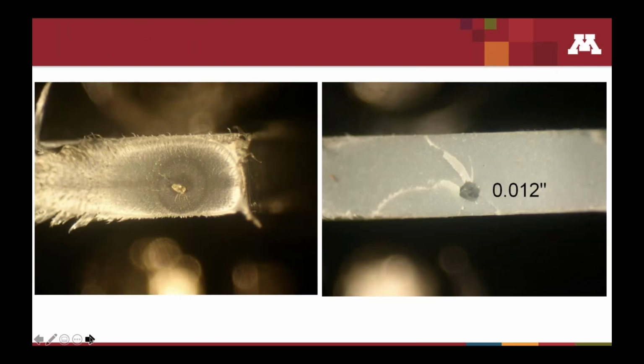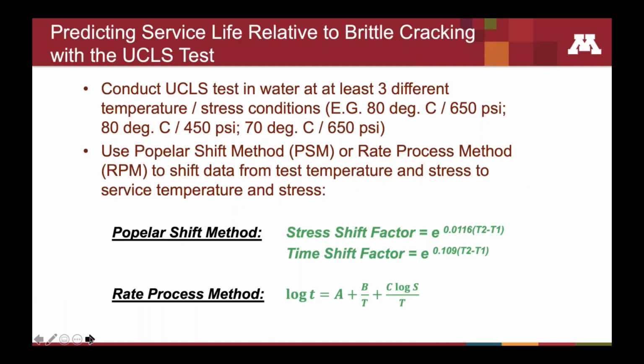So these are some images of contaminants that generate cracks in the specimen, and that was very typical of what we saw. So the way then we related that cracking time to service life is to conduct that test, that UCLS test as we called it, at least 3 different temperature stress conditions.